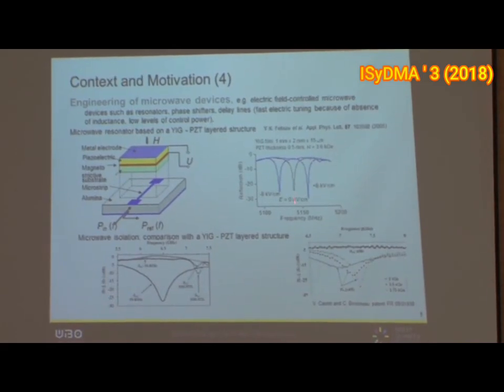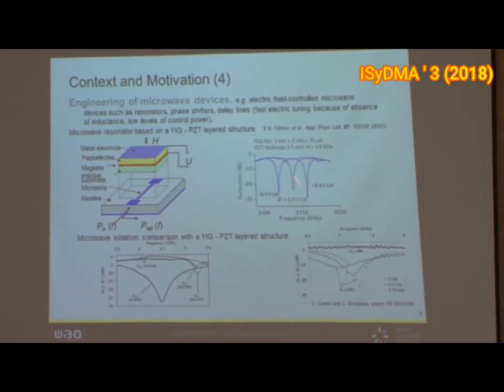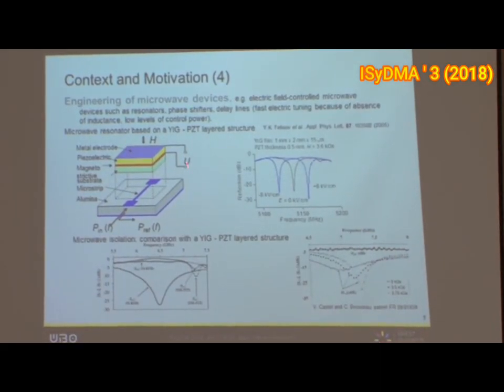What they observed is that there is a peak centered here, and they can blue shift or red shift this peak by applying a voltage gradient right here.